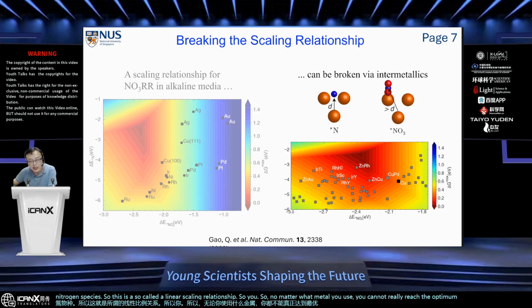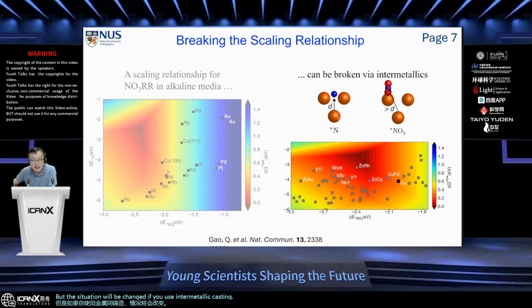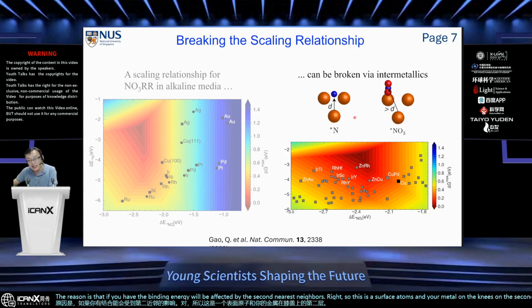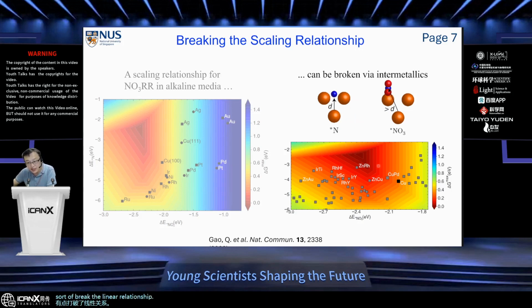But the situation will change if you use an intermetallic catalyst. The reason is that the binding energy is affected by the second nearest neighbors. So this is a surface atom, then the metal underneath on the second layer will be able to affect the binding energy, so as to break the linear relationship. And you can see there are different combinations of intermetallics.